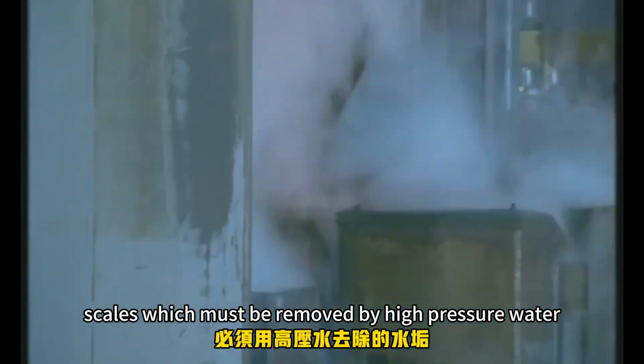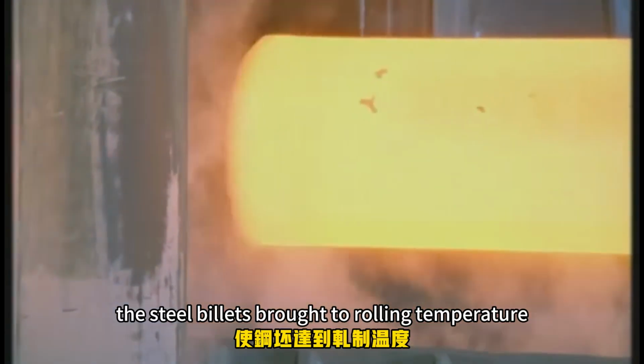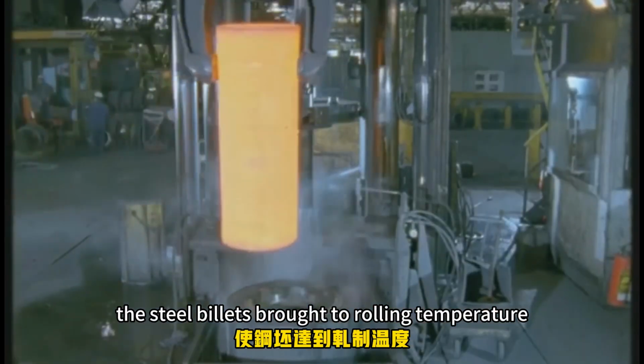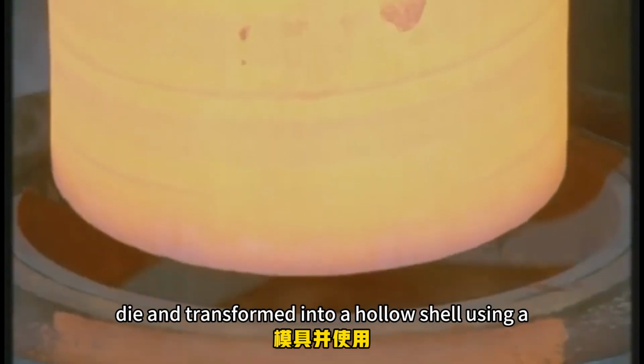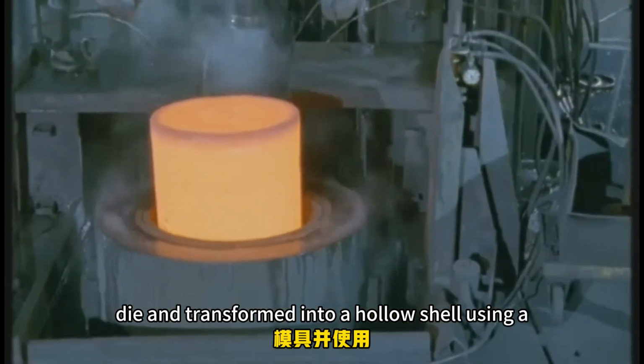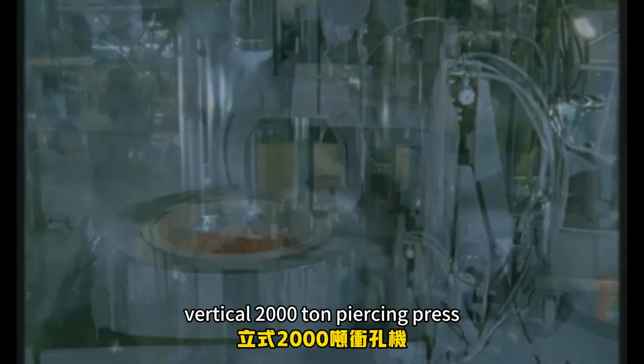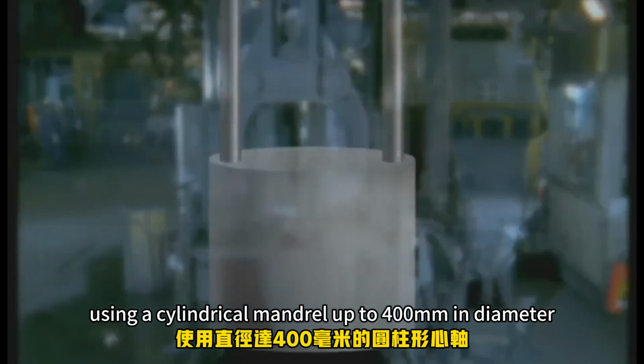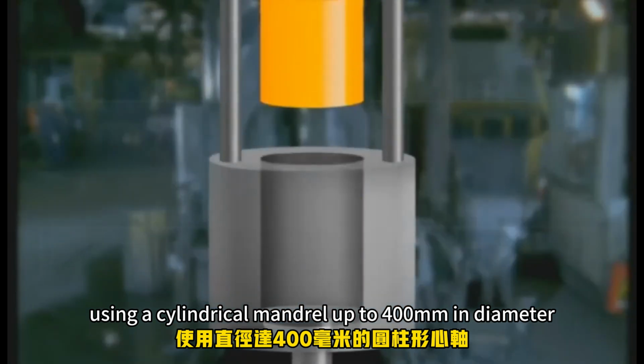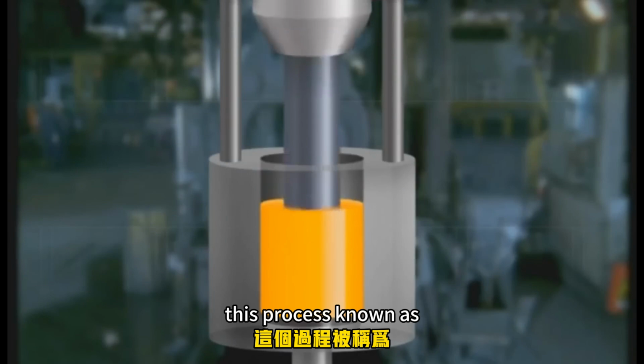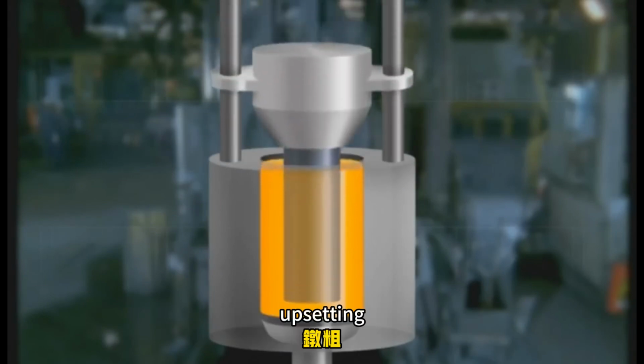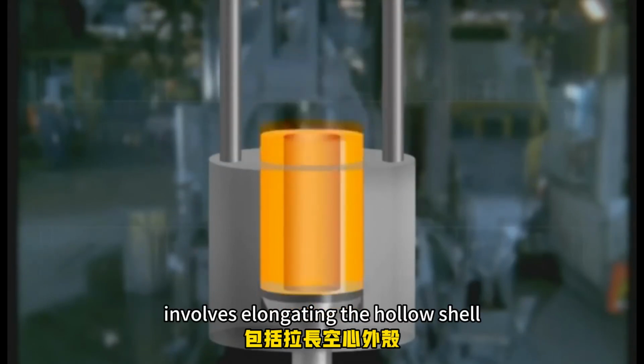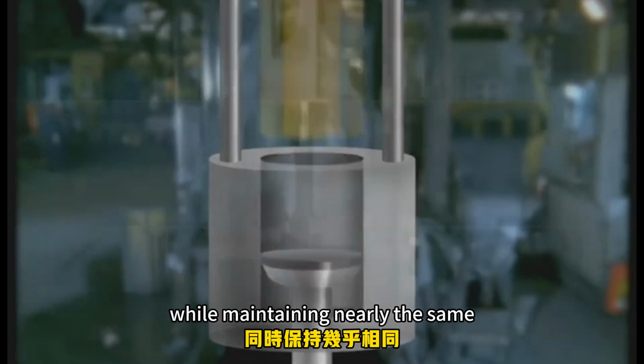by high-pressure water. The steel billets, brought to rolling temperature, are placed into a round die and transformed into a hollow shell using a vertical 2,000-ton piercing press using a cylindrical mandrel up to 400 mm in diameter. This process, known as upsetting, involves elongating the hollow shell while maintaining nearly the same outer diameter.